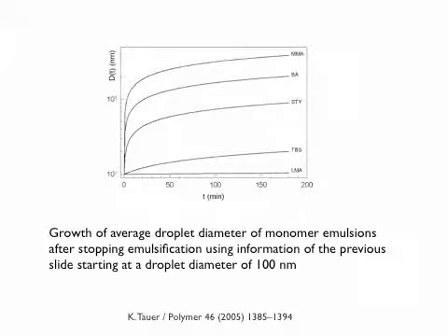Now, if I go to styrene, remember, it has a water solubility of like 3.5 millimoles per liter. So it's not that water soluble. But again, it ripens pretty quick. From 100 nanometer, 50 minutes later, you're at 500 nanometer. So again, you no longer have this very, very nano confinement. So only lauryl methacrylate, which has a very, very long aliphatic chain, seems to remain stable over a prolonged period of time.